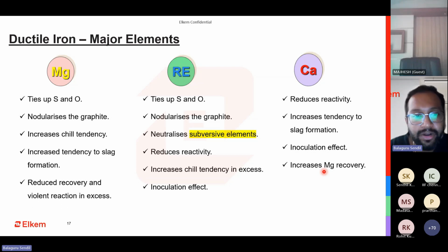Again, from a foundry perspective, for people who are in sourcing or people who regularly use FSM, when they are saying that they are offering you 6 to 7% magnesium, it has to be balanced with your rare earth and calcium. If the calcium is not balanced with your high magnesium and rare earth, then your reaction violence will not be very controlled. Then you will end up getting more slag, and most of the amount is wasted. So these are the most common elements that you have here, and they need to be correctly balanced.